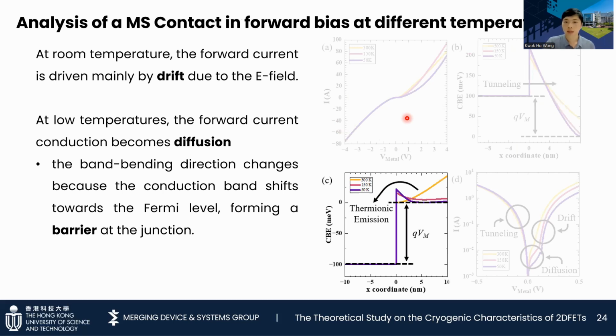In the forward bias, the current at room temperature or high voltage bias is mainly driven by drift due to the E field at the junction forcing the electrons to move from the semiconductor side to the metal side. However, at low temperature, we can say that the forward current mechanism becomes diffusion, because the band bending moves closer to the Fermi level, resulting in the built-in potential in the metal-semiconductor junction. Therefore, the built-in potential blocks the carrier flow and results in the reduced current at the low voltage condition.